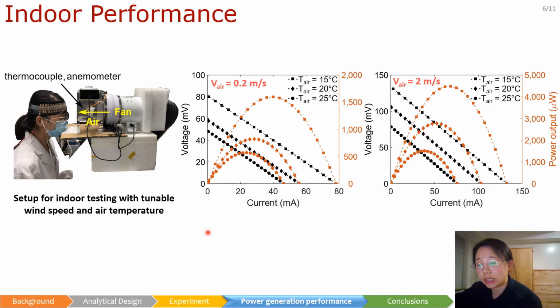In indoor testing, the typical power generation as a function of sweeping current of the device, consisting of 50 pairs of P-type and N-type thermoelectric pillars, is given on the right figures. The three curves are at different temperatures, 15, 20, and 25 degrees C. The first one is under little wind condition, and the other is at a wind speed of 2 meters per second.